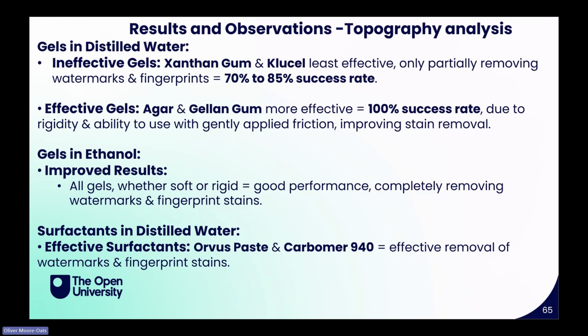The results were that, based on topographic analysis, we were able to quantify the percentage of success. All in all, we have some less effective gels: the soft gels, Xanthan Gum and Klucel, had only a 70 to 85% success rate. But our agar and gellan gum, our hard gels, had a 100% success rate due to the ability to apply them gently with friction, like a rubber. Our gels in ethanol, however, had a 100% success rate, which is not surprising. And our surfactant as well had effective removal of watermark and fingerprint stains.